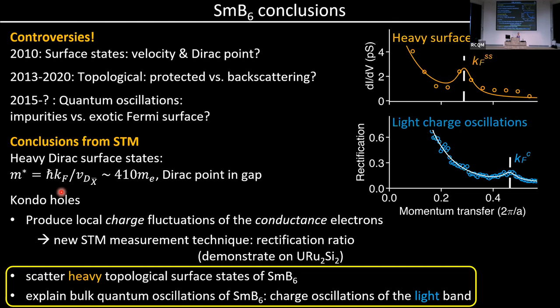Yes. But there's also the counteracting effect, because basically what you said in the second half of your talk, when you take the boron octahedra away, you also reduce the Kondo screening. That's what's referred to by Piers Coleman as the surface Kondo breakdown. And it's also described, for instance, by Jim Allen in the 2016 paper. So I think there are two effects here counteracting each other. And if you look in the X-ray absorption spectroscopy data, actually they go more towards 3+ at the surface.